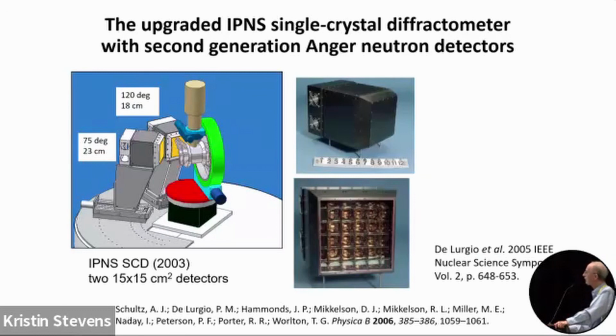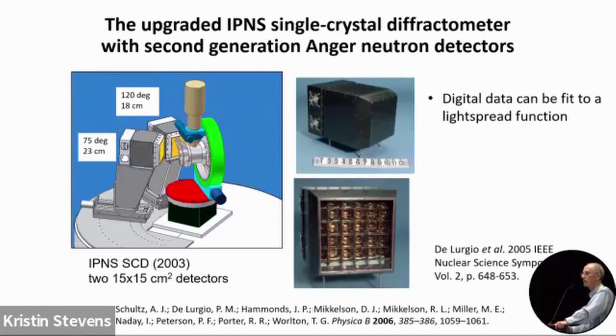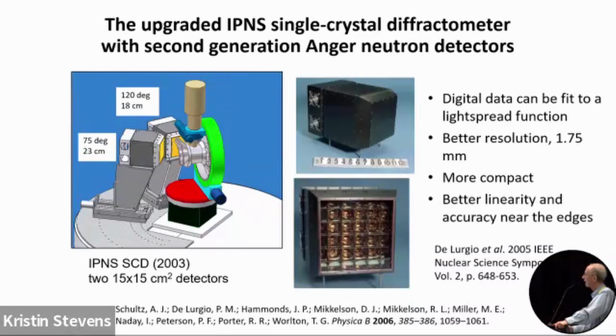The major advance here is that the detector puts out a digital signal rather than analog. That allows the digital data to be fit to a light spread function, typically a Gaussian, which turns out to be more accurate than doing the centroid calculation. So now the resolution is down to 1.75 millimeters. These detectors, as you can see, are more compact, and there's better linearity and accuracy near the edges, again, because we can fit the light spread function. This detector was mostly designed and built by Pat De Lurgio at Argonne.